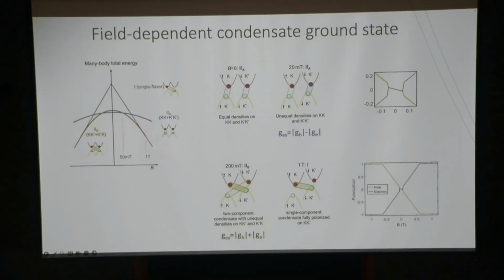But then up to a critical magnetic field, the inter-valley exciton takes over because it has a larger G factor. It can benefit from the exchange, the Zeeman splitting better, and then it will finally get a crossover and have lower energy. So you have a first order phase transition into this inter-valley exciton condensate. And then they will have a larger G factor. So basically you have a larger slope until everything gets fully polarized.